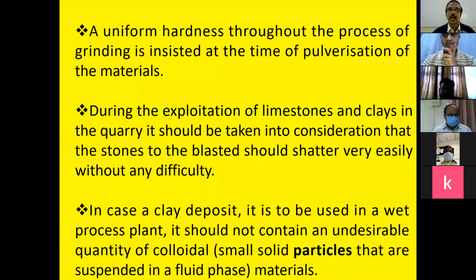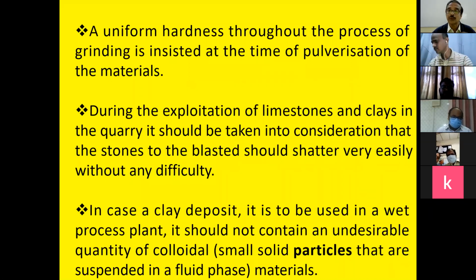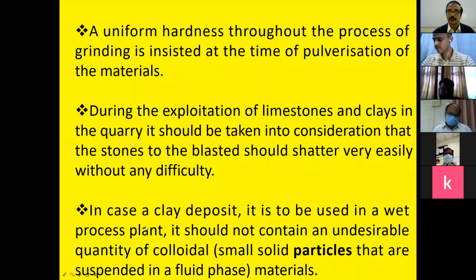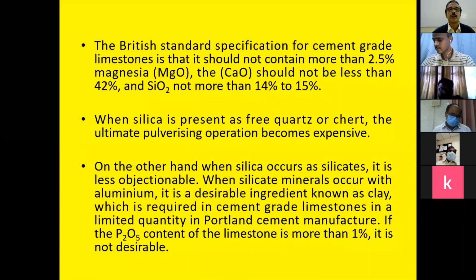So during the exploitation of limestones and clays in a quarry, it should be taken into consideration that stones that are blasted should shatter very easily without any difficulty. If we are not able to blast it easily, it means hardness plays a very important role. That means variable hardness is there in such material. So even if you take it out, it will pose problems during the pulverization. So that has to be taken care of. In case of a clay deposit to be used in a wet process plant, it should not contain an undesirable quantity of colloidal material, that means small solid particles that are suspended in a fluid phase. The British standard specification for the cement grade limestone is that it should not contain more than 2.5% of magnesia. The CaO should not be less than 42% and SiO2 not more than 14% to 15%. So this standard has to be maintained.